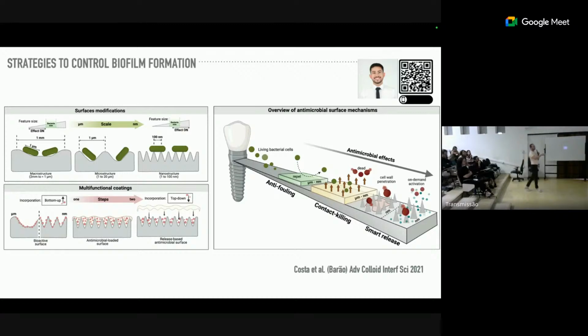In terms of coatings, we have different techniques that we call bottom-up or top-down, or the combination of both. The bottom-up is the formation of this coating from the bottom. For example, anodization, plasma electrolytic oxidation. We're going to oxidize the surface from the bottom, and then a thick oxide layer is going to be formed. This is very interesting because if you are not depositing something, the adhesion between the coating and the substrate is very high.